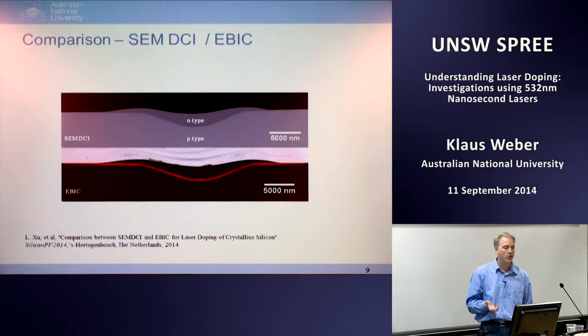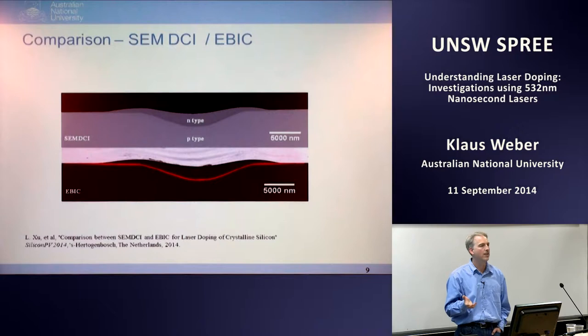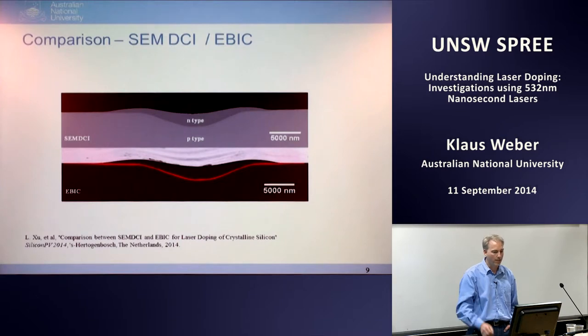And we know from other experiments that there is both a depth limitation and a dopant density limitation, which is maybe around 10 to the 18 or high 10 to the 17 per centimeter cubed. So anything below that we don't pick up very well with the SEM technique.